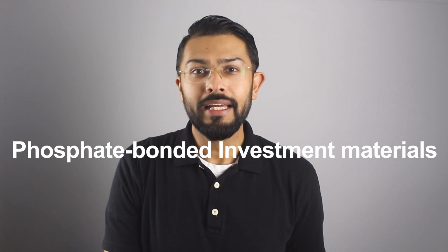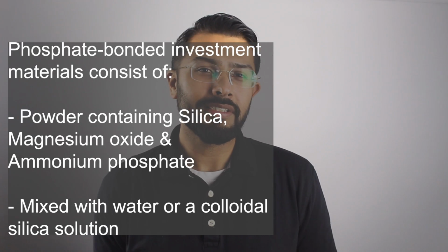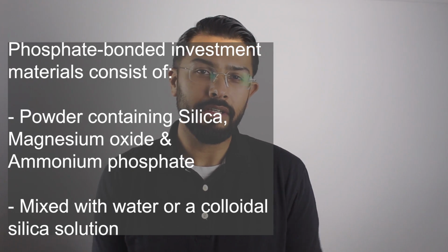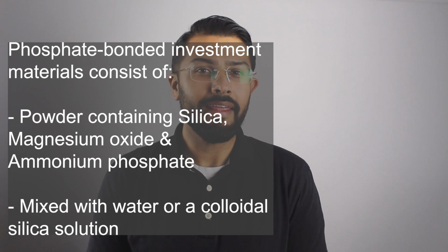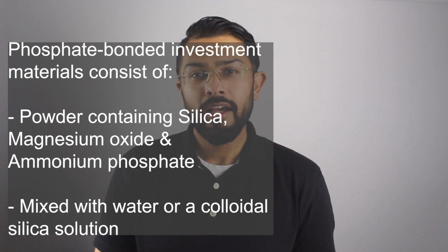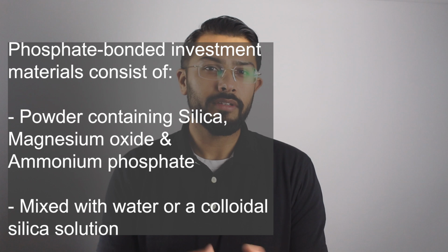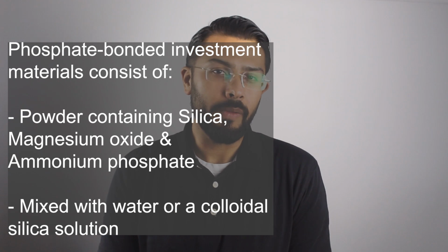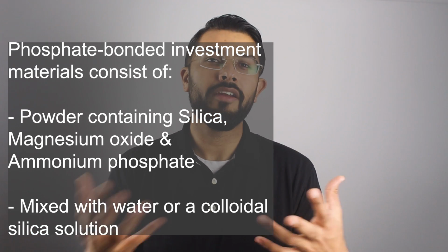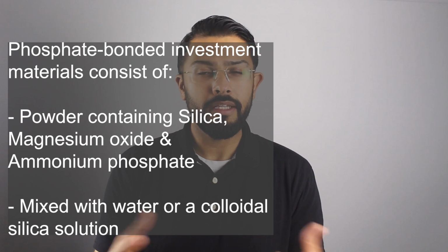Now let's talk about the third and last type of investment material today, which is phosphate-bonded investment materials. These materials consist of a powder containing silica, magnesium oxide, and ammonium phosphate. On mixing with water or a colloidal silica solution, a reaction between the phosphate and oxide occurs to form magnesium ammonium phosphate. This binds the silica together to form the set investment mold.